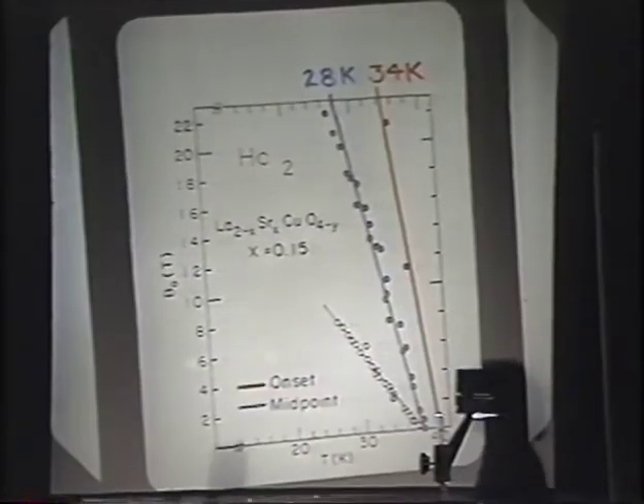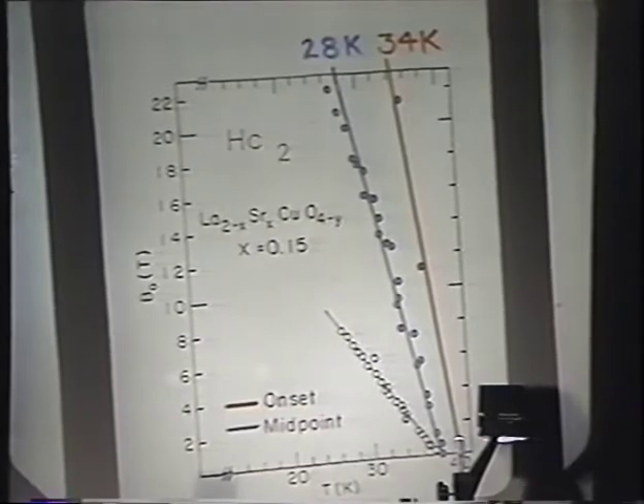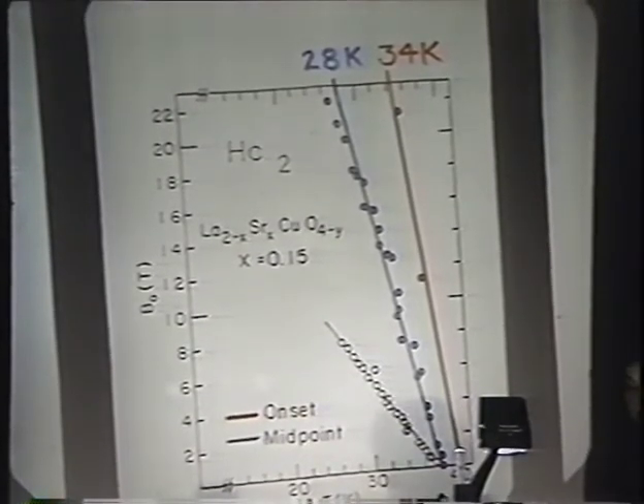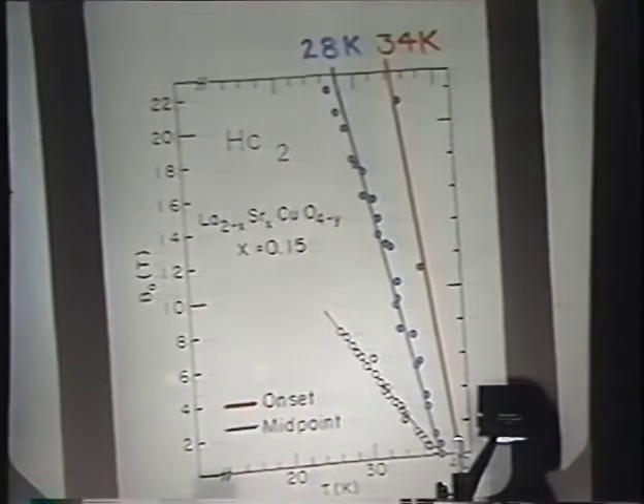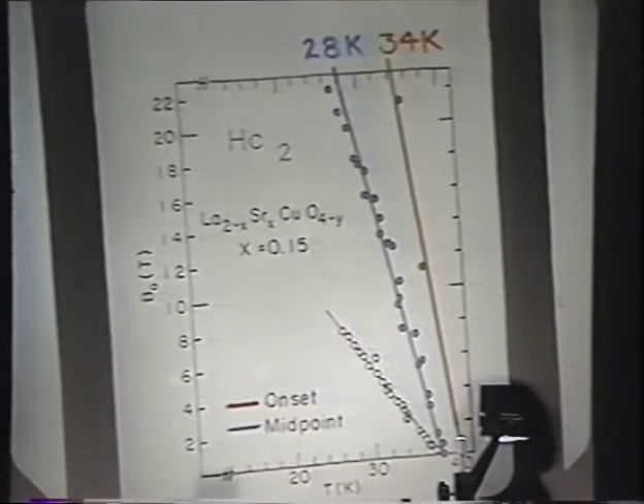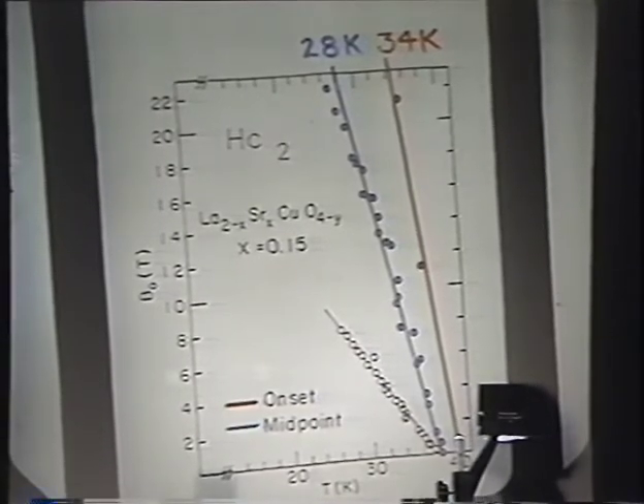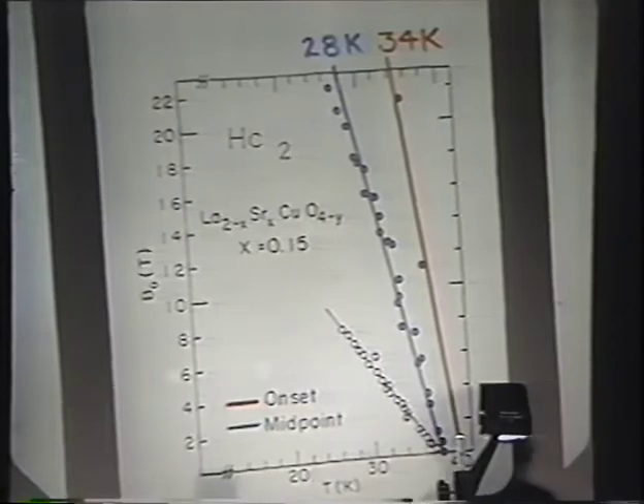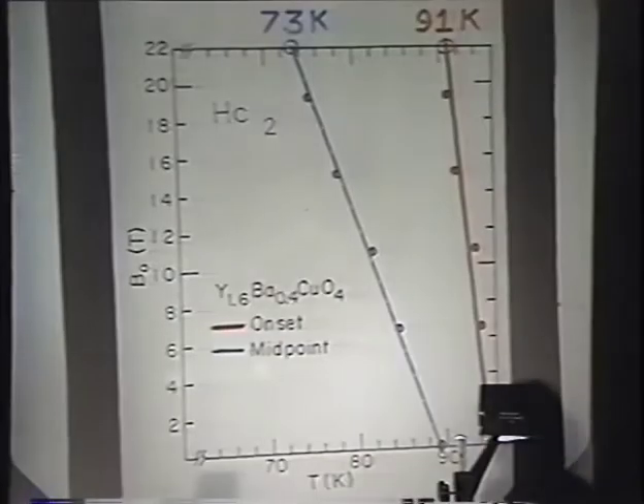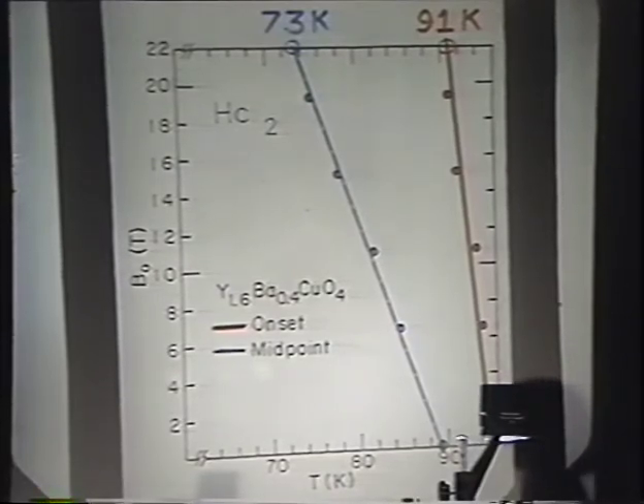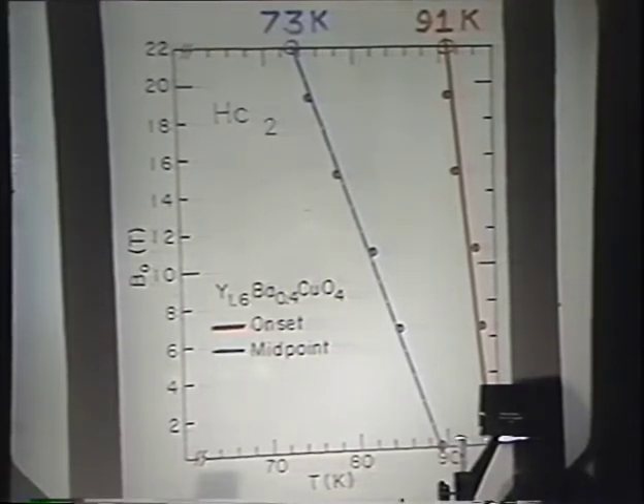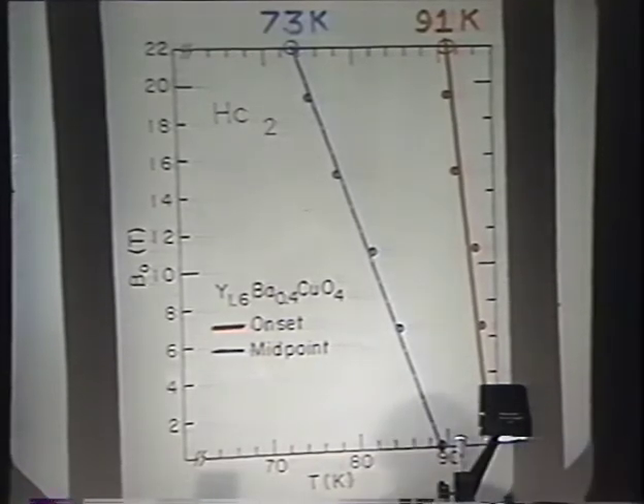The upper critical fields of these materials are shown here. These are the measurements. The red line is the onset of superconductivity, and the blue line is the midpoint of the resistive transition in the lanthanum strontium copper oxide materials. This is the 0.15 again. Note that at 22 Tesla, the Tcs for the onset and the midpoint are 34 and 28 Kelvin respectively. For the yttrium barium material of our early work, we show the same curves, the red being the onset of the transition, and the blue line being the midpoint of the resistance transition. And again, at 22 Tesla, we find that the Tcs are dropped to 91 for the onset and 73 for the midpoint.